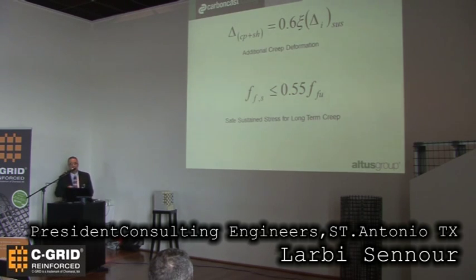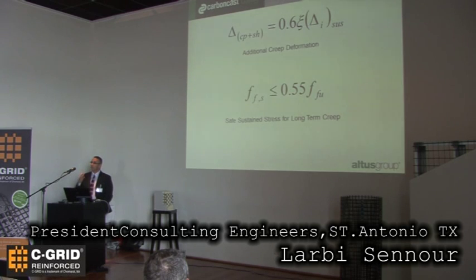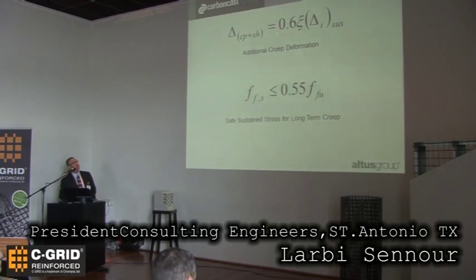For creep and shrinkage, we have done a creep test, and the formula is there. If you want a long-term creep, it's 0.6 times the creep coefficient. This is the standard concrete creep coefficient, the same as in the Eurocode, times your sustained deformation. So if your sustained deformation is 5 centimeters, you take your creep coefficient times 0.6, and you get your long-term creep and shrinkage. That has been tested, and this formula verified.